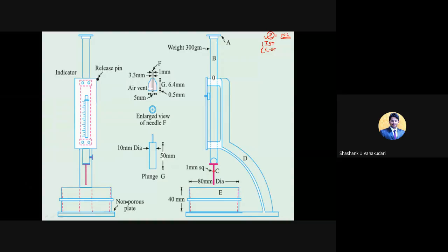You should go on conducting that experiment so that at 1 percentage you have to stop the trials. At what penetration value will you stop the test? I said that the penetration value should be 33 to 35 mm. Correct? So you should go on adding the percentage of water and note down every trial's initial reading as well as the final reading.